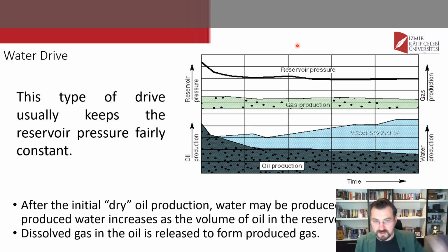And the typical behavior for the water drive, as you can see here, for the reservoir pressure, oil production, and gas production. So gas production shows a little decrease, not too much decrease or increase, but a very slight fluctuation. Your oil production is lowering by time, but your water production is increasing by time. So you have to manage it well to slow this increase. It will increase, no way out, but you have to slow it. Instead of 3 years, maybe you can see it in 5 years.